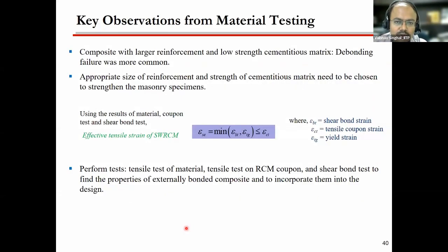Okay, so these are some of the summary. We have done a lot of tests in the lab, different types of reinforcing material, different types of cementitious matrix. It is generally seen that if you use a larger amount of reinforcement and your cementitious matrix is of a lower strength, then debonding will be the common failure mode. So it is suggested that you use an appropriate size of reinforcement and also a good strength of cementitious matrix. Something like you have to use at least 1:3 or 1:4 cement sand mortar for strengthening using